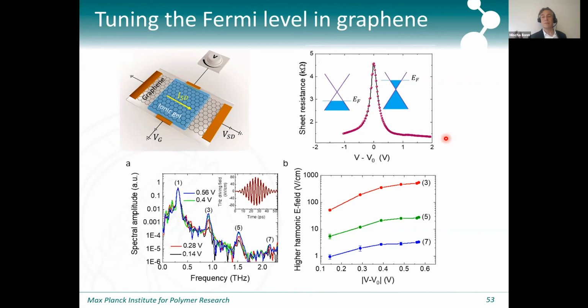After that you have a coherent terahertz beam that you can then manipulate, and we read it out with electro-optic sampling, where we have a delay line and we delay a 30 femtosecond 800 nanometer pulse to sample the quasi-instantaneous field strength within the terahertz pulse. We do all sorts of experiments in our lab, and this is really the simplest. It's not difficult.